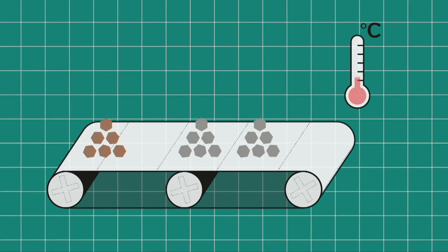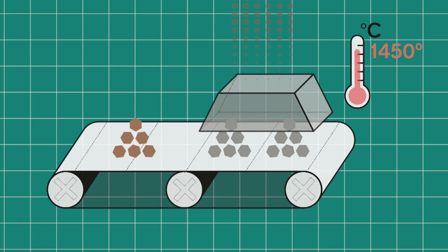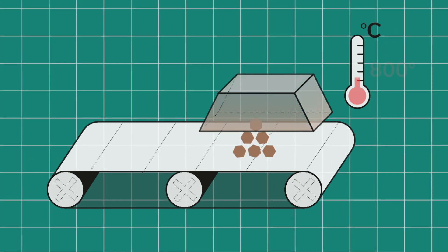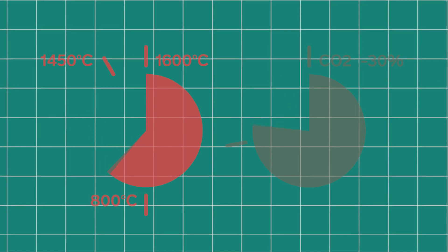How does one make ecological cement? During the manufacture of cement, most of the carbon emissions come from the decomposition of limestone. We can partly replace the clinker — the resulting component — with clay. There's hardly any CO2 in clay, and to activate it, we only need to heat it to 800 degrees Celsius for less than one hour, instead of the 1,450 degrees necessary in normal cement production.